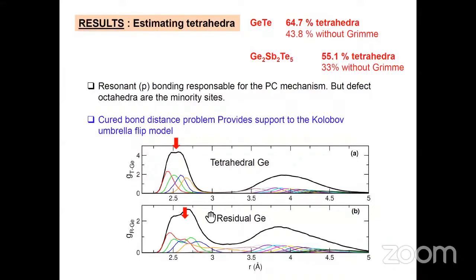This is at variance with the residual Ge, which, as you can see, first has a main peak which is shifted to larger distances, and which has a very complex population. That signals that you have indeed a defect octahedral site. We have coordination defects, 3-, 4-, and 5-fold germanium, and some of them extend to the second shell because you have long and short bonds in this kind of geometry.